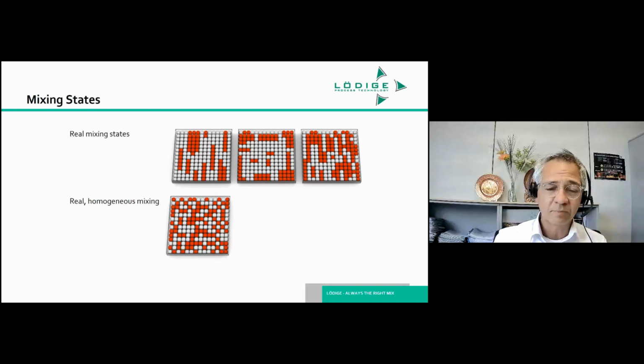And in real life, depending on the formulation, in this case we display it by just using colored particles, red and white. You get, looking at the upper row, more or less an unevenly mixed state. You have more or less of certain particles in the mixture, and sometimes they're not equally distributed. And this can have an effect on your cell properties and on any property afterwards for a given product. So the idea of using mixing equipment is to get all these particles as homogeneous as possible in real life. They won't look as in the ideal state, but there can be, as you see here at the bottom, a more realistic homogeneous state where it's more or less mixed ideally.